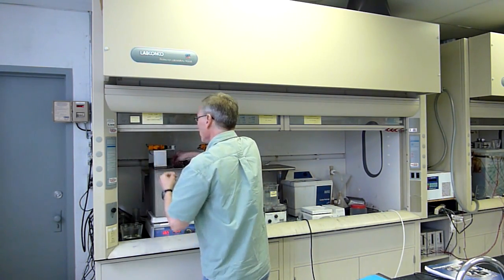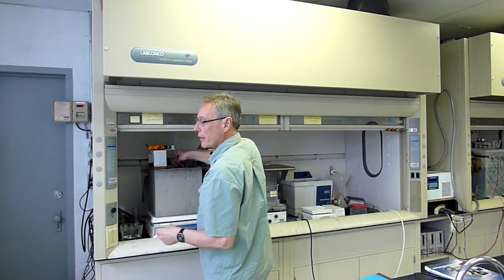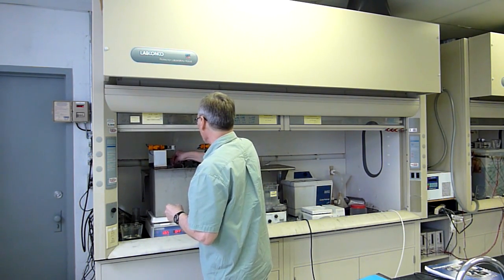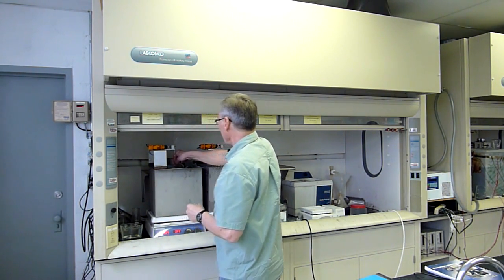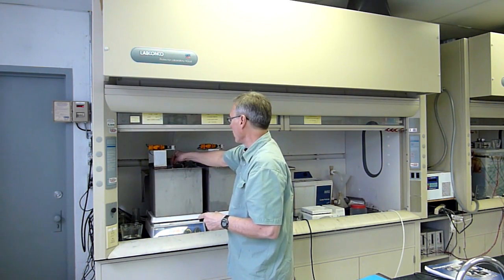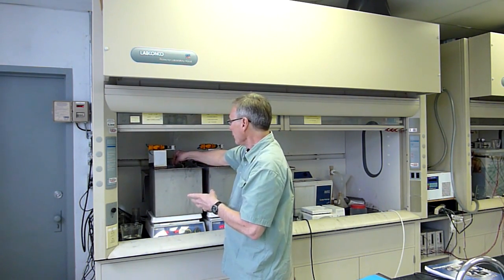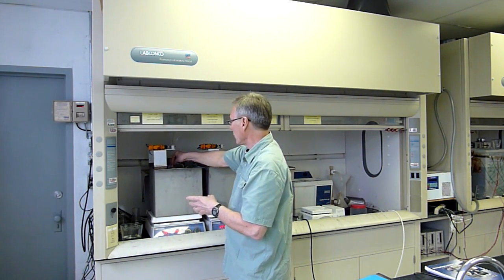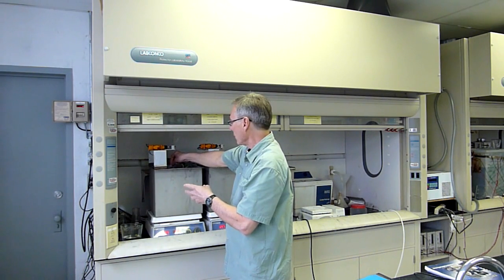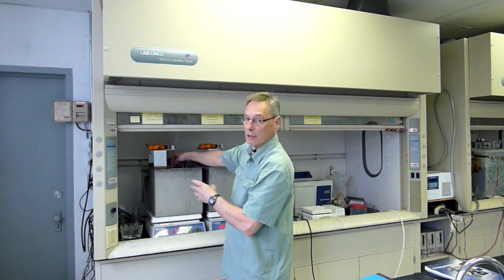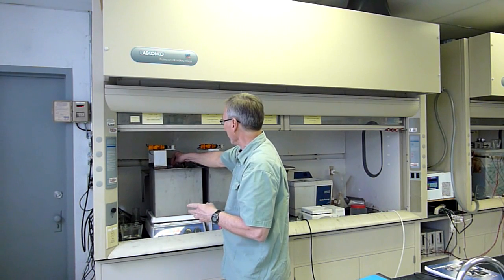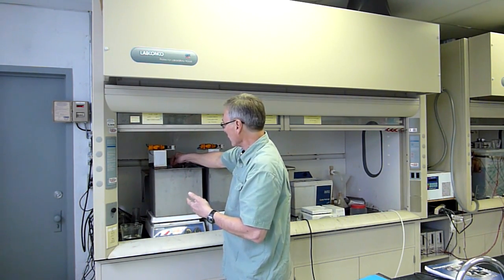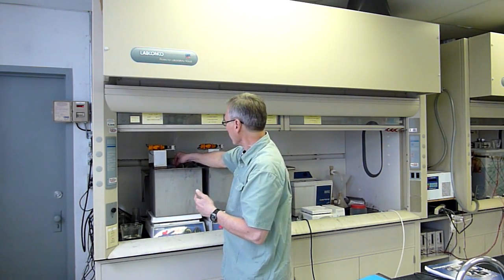And we're in the solution. Double checking our current. See we're at .25 amps right now. 250 milliamps. I like to do a strong manual agitation when we first go into the bath. Your adhesion between the plated gold and your base metal is really being established in the first millisecond to the first few seconds that you're in the bath. So manual agitation helps replenish the solution right at the surface, so you get a strong bond between the plated gold and your base metal.